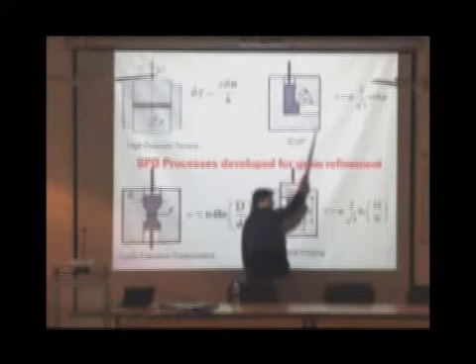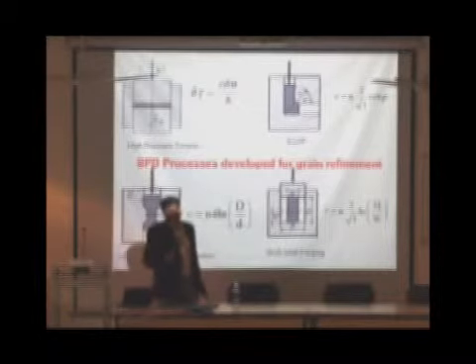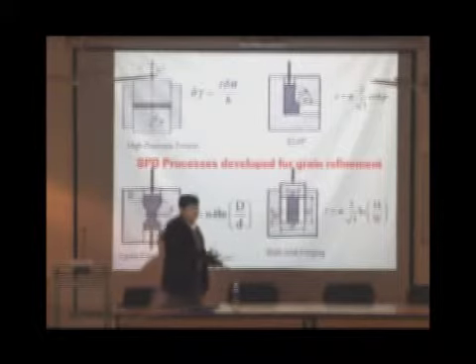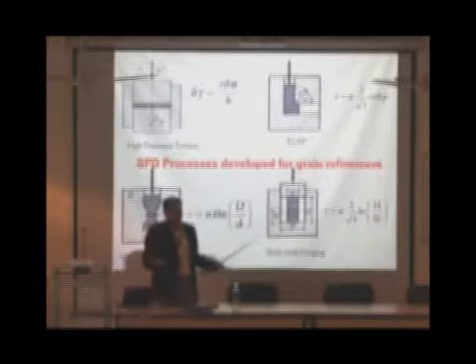The beauty of this process is we are applying shear strain at this place, and the end product that we are getting is of the same cross section. We are putting the metal of 10mm or 1 inch diameter and getting the same output. If we are putting a coarse grained metal from here, we are getting a bulk nanomaterial from here of same billet but of high strength.